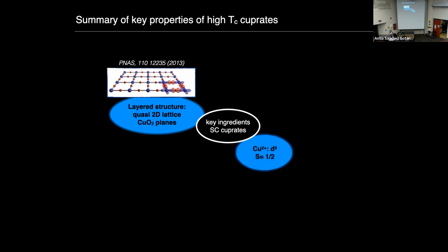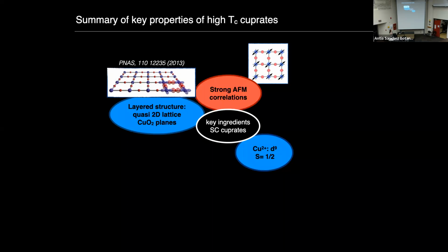In addition to that, in the parent phases, the copper is always in a 2+ d9 configuration. That leaves us with a spin 1/2 system with strong antiferromagnetic correlations and the involvement of a single band of dx² minus y² character around the Fermi level.